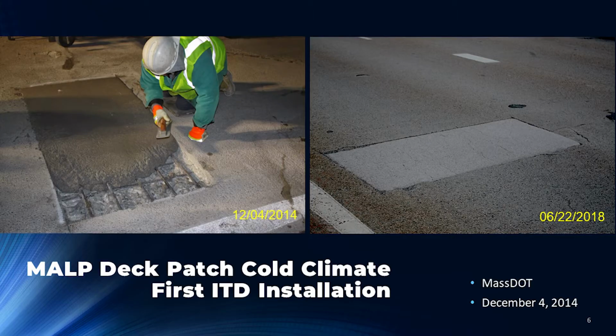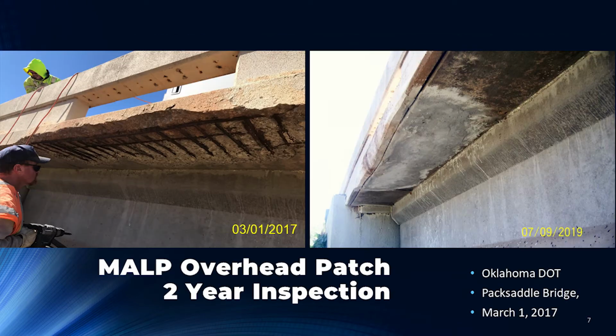And again, this repair was performed in 30-degree temperatures using fast set admix, so still traffic ready in an hour or less. This is another application that we did. This is on the Packsaddle Bridge in Oklahoma. We used 47 pails of our Phoscrete VO, which was installed with no sandblasting.